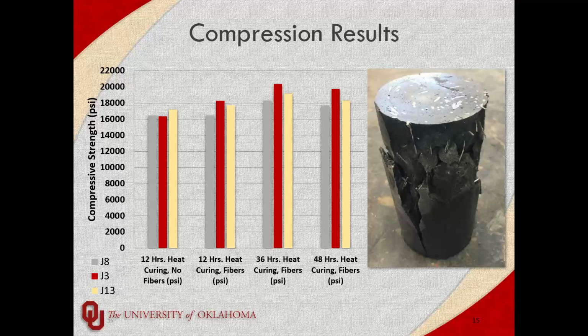You want higher flowability because it's obviously going to flow much better through these congested areas that you want to use them for. But the higher flowability you have, the less likely, even with the Dramix fibers, you are to keep them suspended. So you end up with a lot of segregation. I've even seen that with the Dramix fibers that we've used in our lab. Start getting above 10.5 inch flow, they don't tend to stay suspended, which becomes a problem.